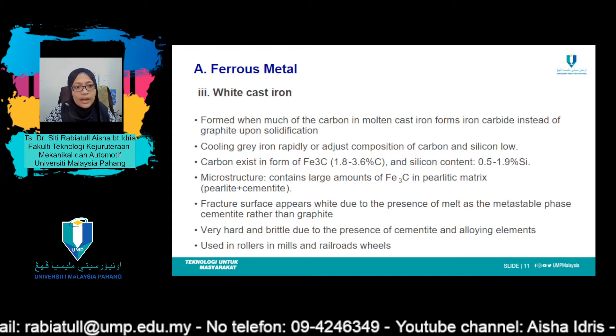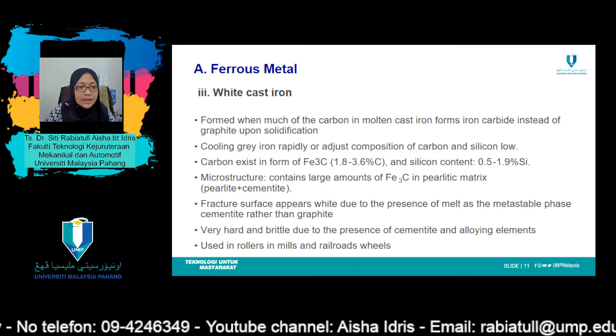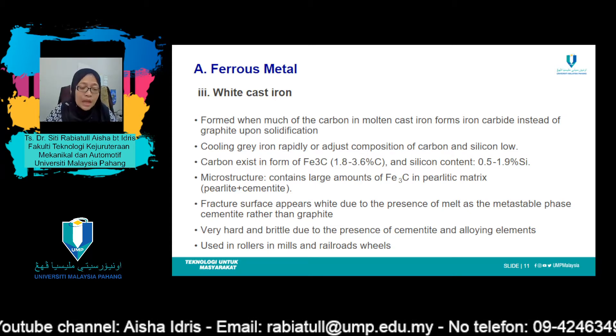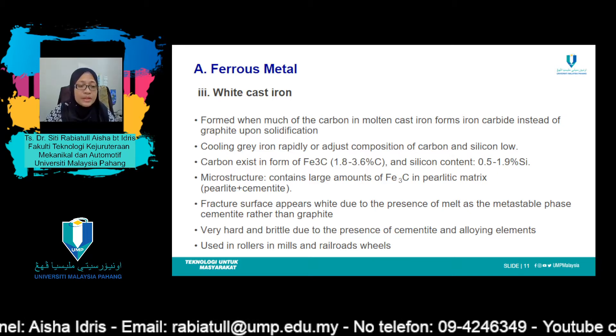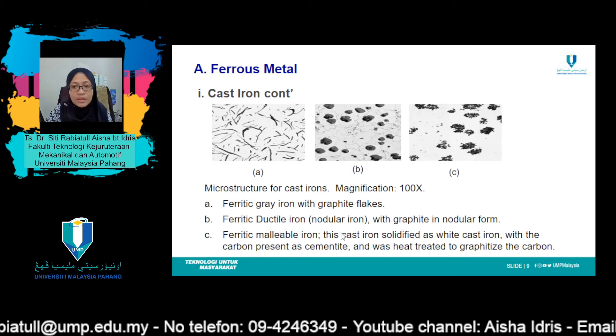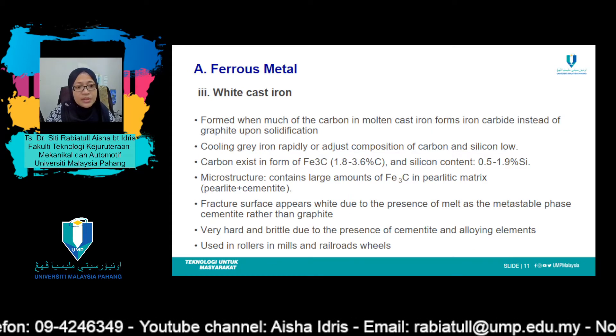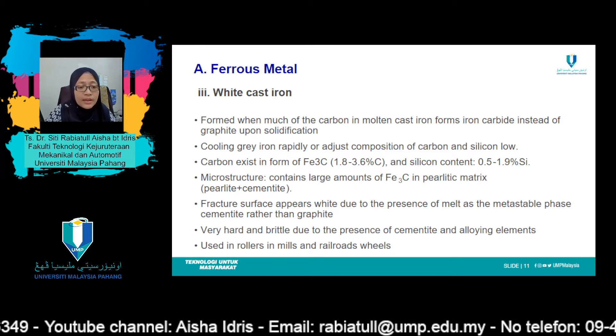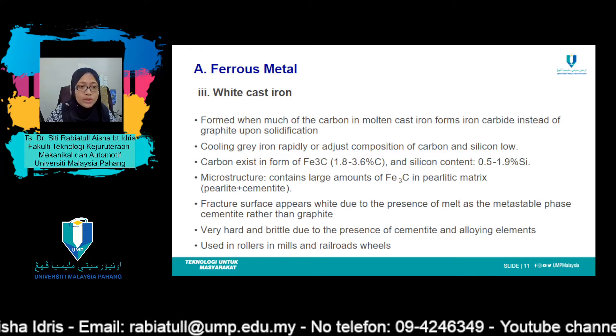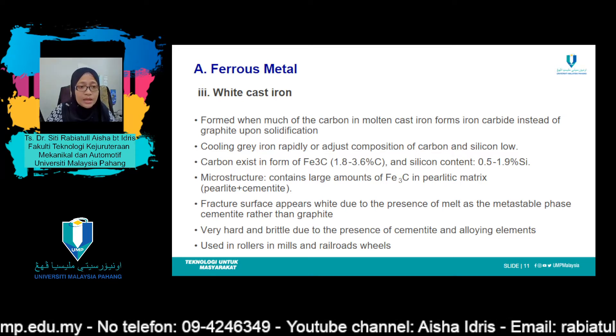For low silicon cast iron and rapid cooling rates, most of the carbon exists as cementite instead of graphite. The fracture surface of this alloy has a white appearance, and thus it is termed white cast iron. The photomicrograph in figure C shows the microstructure of white cast iron. Thick sections may have only a surface layer of white cast iron that was chilled during the casting process; gray iron forms at interior regions which cool more slowly. As a consequence of the large amount of cementite phase, white iron is extremely hard but also very brittle.